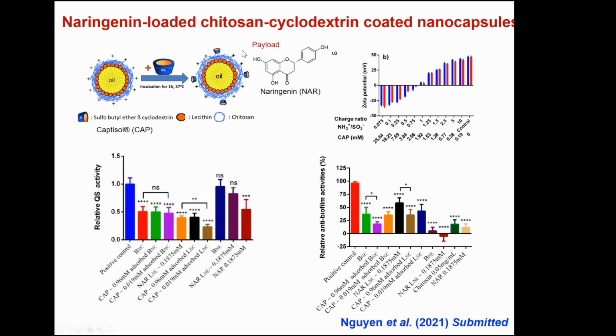positive surface charge, it is possible also to use layer-by-layer technology. And in this case, the nanocapsules are also coated by a sulfobutyl ether beta cyclodextrin at the surface. So these coated nanocapsules, depending on the amount of Captisol, that's the name of the cyclodextrin, we can also see a reversal of the zeta potential, as we see in the upper right-hand corner.